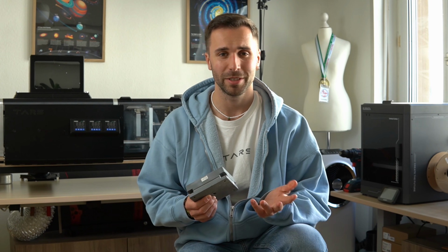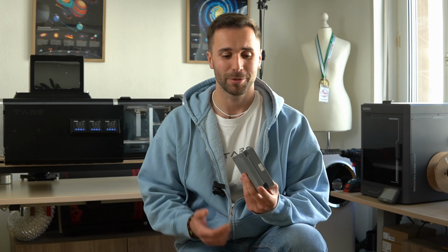After running several cycles and molds, I am honestly very much surprised by how well these resin molds hold up. They last much longer than I expected, and even though the material gets exposed to 250 degrees Celsius when injecting polypropylene, and the material is only specified for 220 degrees Celsius, that really speaks for the strength and heat resistance of this TR300 material. And just to be clear, I'm not sponsored by Formlabs in any way. I use this material since a few years, and I think it's honestly just really cool how that product can be used for this type of application.